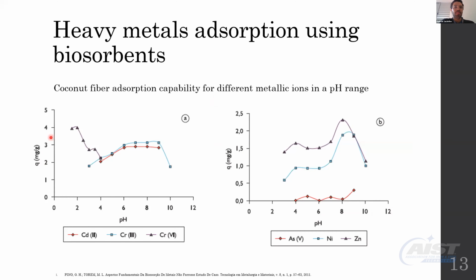In this graph, the adsorption capability of the coconut fiber across the pH range is presented for some metallic ions. The trivalent chromium and the cadmium between pHs 3 and 9 tend to adsorb more in this range of pH, but the hexavalent chromium tends to drop its adsorption capability with the increase of pH. This falling indicates that there must be competition for the binding sites on the fiber surface between different types of ions at high pH values.